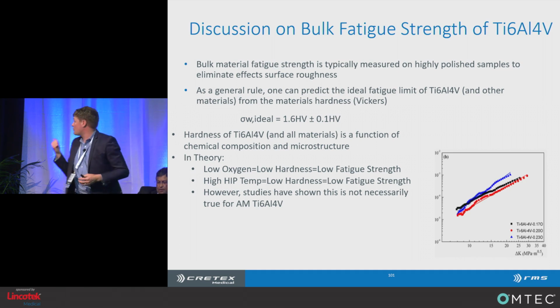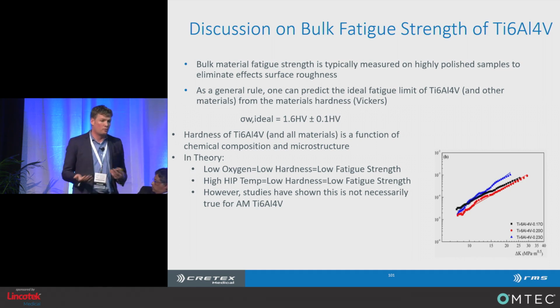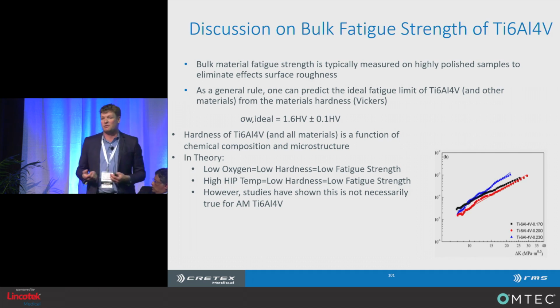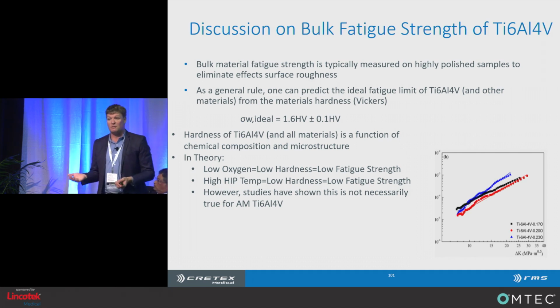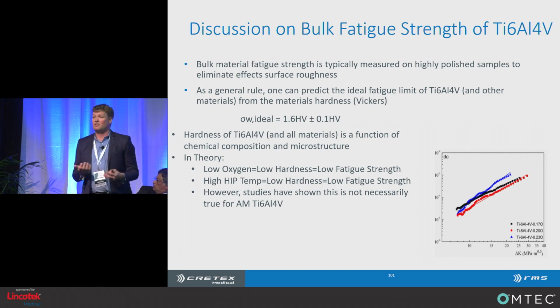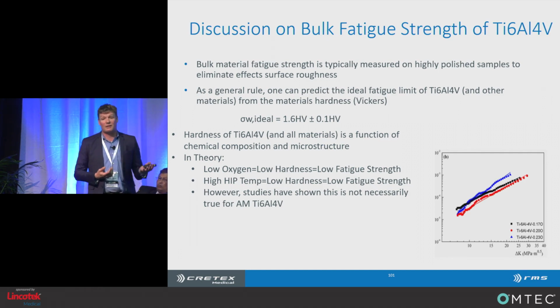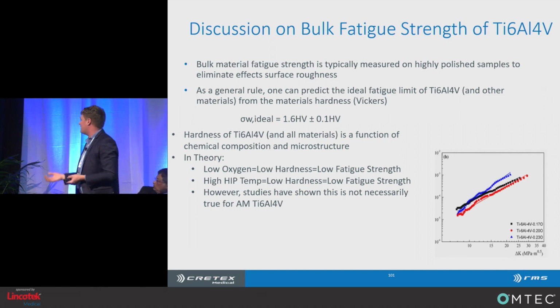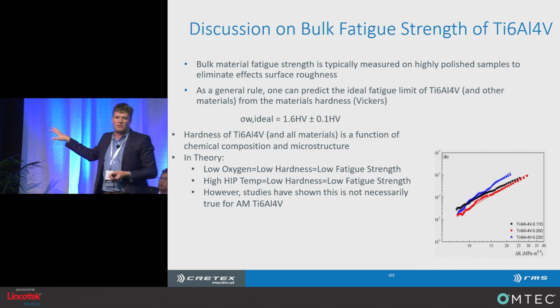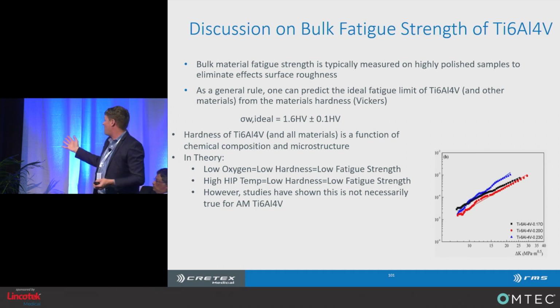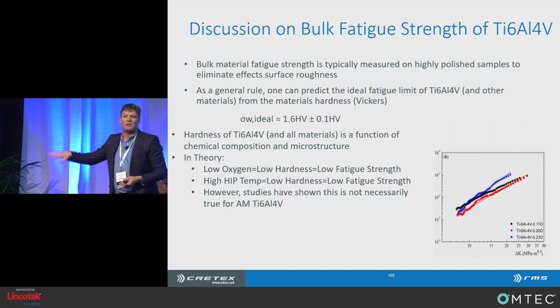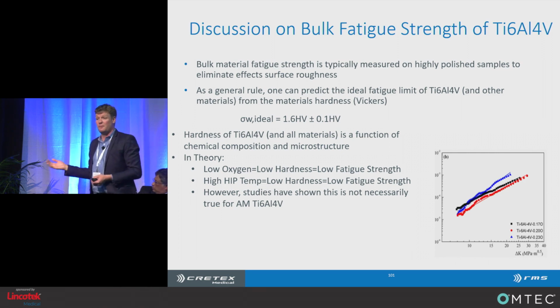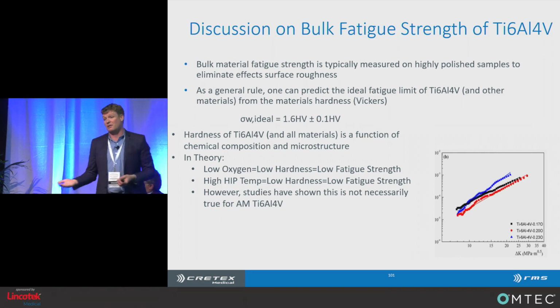The graph up here is a really good example, right? One of the rules of thumb is as oxygen content in the material increases, the fatigue strength should go up, right? But in general, the strength actually increases. And you can see here that if you looked at just this particular study, there seems to be an optimal amount of oxygen at 0.17 in which you get the best fatigue performance. At higher oxygen, you actually get worse fatigue performance. And at low oxygen, you actually get worse performance.